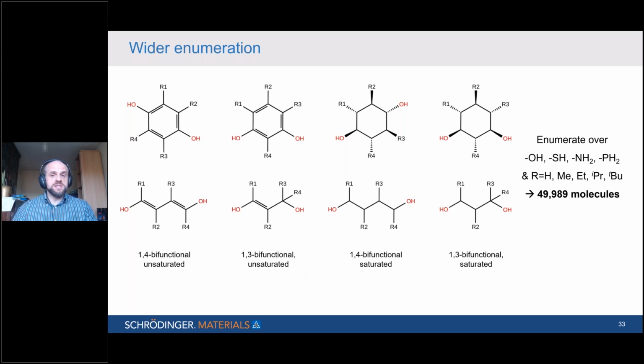Maybe these wouldn't be so good for MLD because they might allow the two OH groups to attach to the same surface, but if the R groups were bulky, we might get away with it. So it could be interesting just to see if that's a significant thing for the volatility. So enumerating over all of these, and then also enumerating over thiols, amines, and phosphines instead of the OH groups, and enumerating over all the R groups, gives us a data set of 49,989 different molecules. But the volatility model is very quick to execute. As I said, it takes a fraction of a second. So after about 10 minutes, we had all the predicted temperatures for this set of molecules.